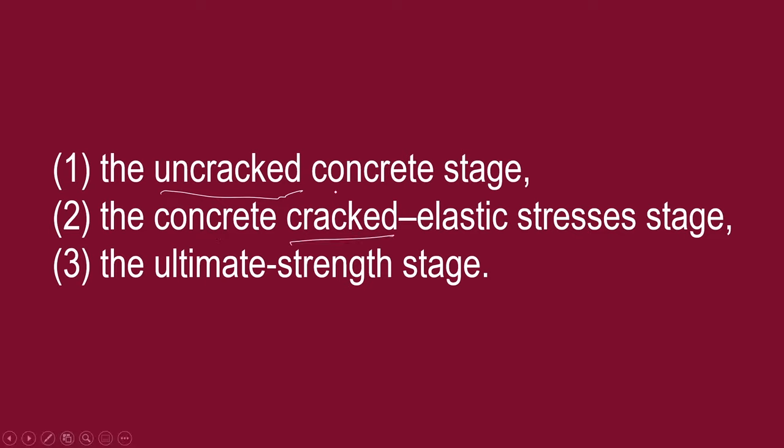So now we will solve the value of the modulus of rupture. The modulus of rupture is equal to 0.62, with lambda of 1.0, multiplied by the square root of fc prime. The given compressive strength is 27.6. Using NSCP 2015, the modulus of rupture is equal to 3.257. Please verify in case my computation is wrong. This is in megapascals.